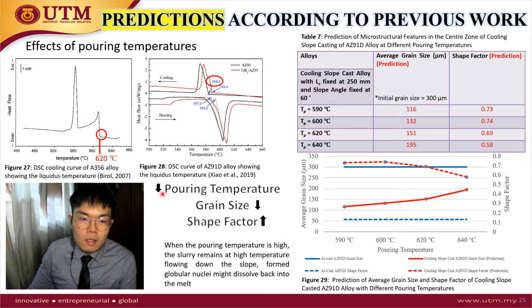When a low pouring temperature is used, we obtain a smaller grain size and a greater shape factor. This is because when the pouring temperature is high, the slurry remains at high temperature while flowing down the slope, and the formed globular nuclei might dissolve back into the melt.